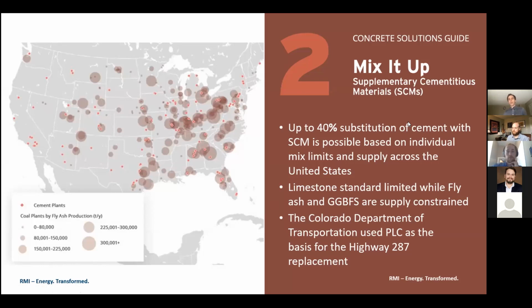So in putting together the guide, we had a look at some of the practical constraints around using SCMs. So thinking, for example, in limestone about the limits that ASTM sets out for how much limestone could be used in a mix because of the impact that it might have on strength, as well as some of the supply constraints, particularly focused around fly ash and slag. And together, looking at those two constraints, we come up with an estimate of around 40% substitution being possible across the US with SCMs. And that in and of itself, because it offsets cement usage, would have the largest impact in terms of emissions of any of the 6 solutions in the guide.